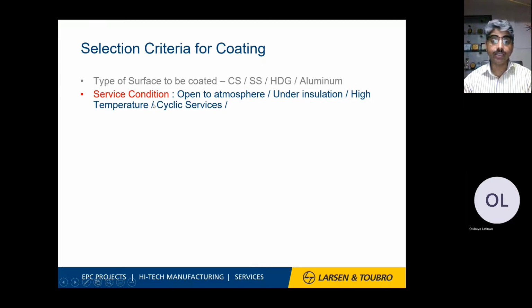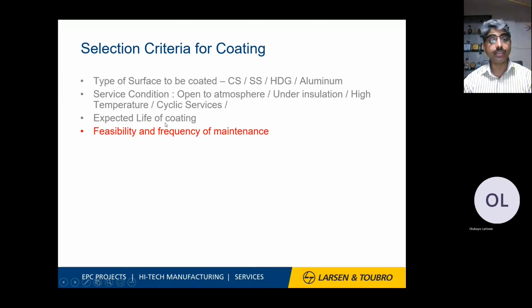Other is cyclic service. Yes, there is a very versatile paint called inorganic copolymer, which is normally a versatile solution for cryogenic temperatures to high temperature, so minus 196 degrees C to plus 650 degrees C. One paint is the solution, called inorganic copolymer paint, which is very popular nowadays in the oil and gas industries. Other is expected life of coating. That is also a major criterion for selection. You can protect your structures for 10 years, 15 years, 20 years, 25 years, or more than 25 years.